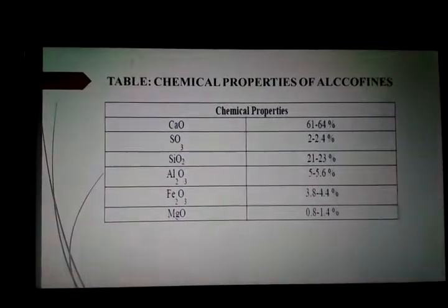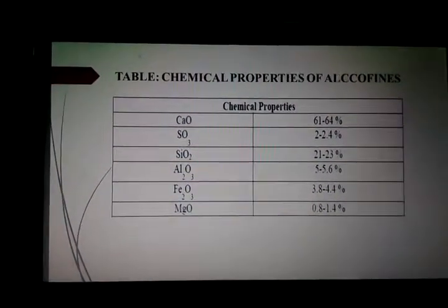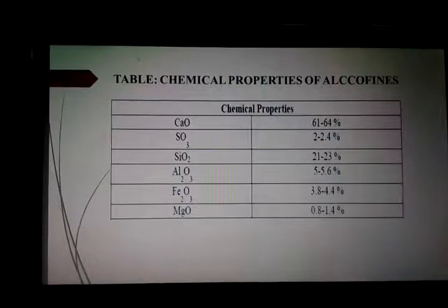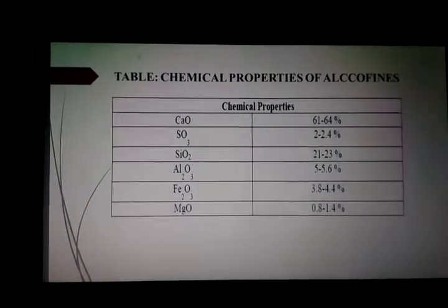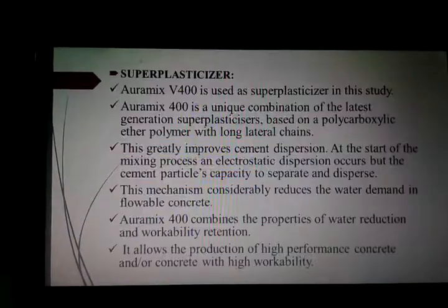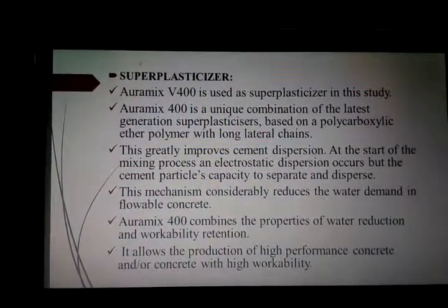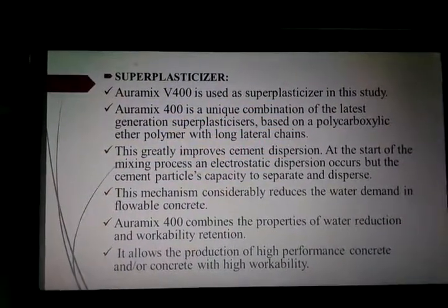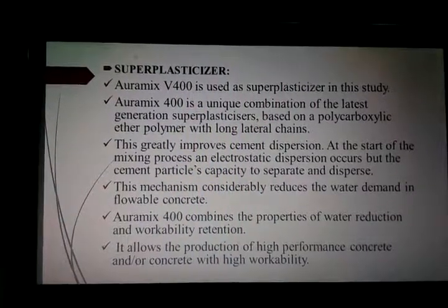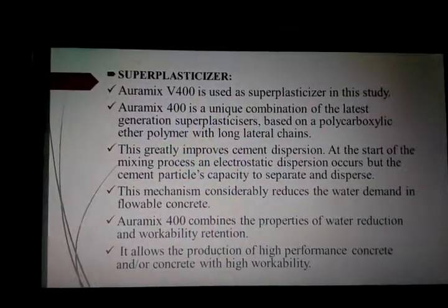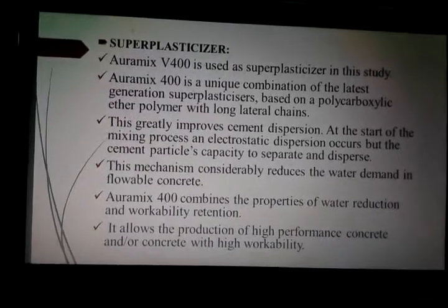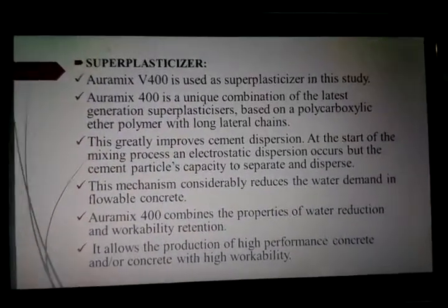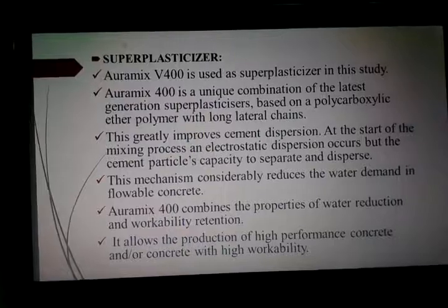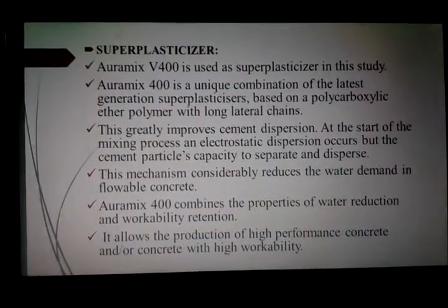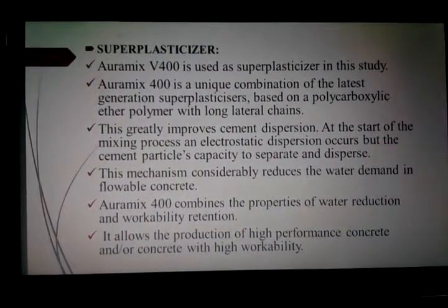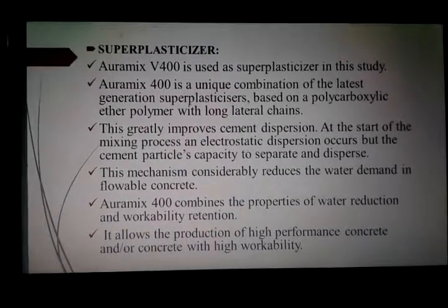Table. Chemical properties of alccofine. This is nothing but the chemical composition of the alccofine. CaO, SO3, SiO2, Al2O3, Fe2O3 and MgO are as given. Superplasticizer. We have used superplasticizer Auramix V400, which is specifically used for this study, and it has a unique combination of the latest generation superplasticizers based on polycarboxylic ether polymer with long lateral chains. This greatly improves the cement dispersion. At the starting of the mix process, an electrostatic dispersion occurs, but the cement particles' capacity to separate and disperse